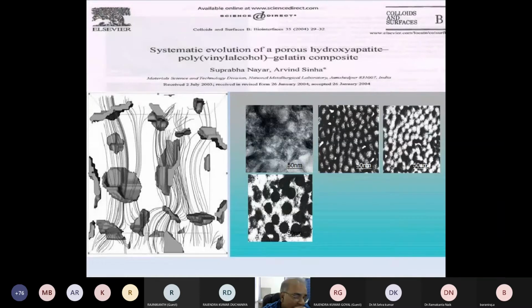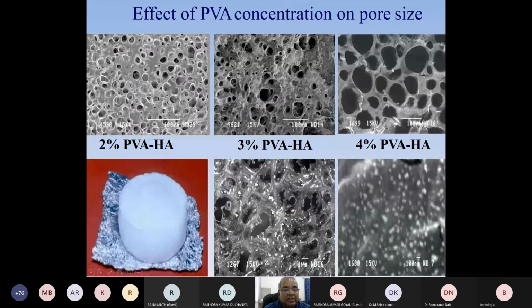And gelatin is water soluble. So we took the gelatin, doped it with calcium ion, then after a few days, subjected it to the phosphate bath. So calcium phosphate salts got precipitated. You can see here at a well-defined size. With time, when we carried out the microscopy, we saw that the clusters of hydroxyapatite start growing and forming a 3D network, which is porous. Something like this. This is our product. After 10 or 15 days, we got such a 3D product, which is a polymer hydroxyapatite nanocomposite.